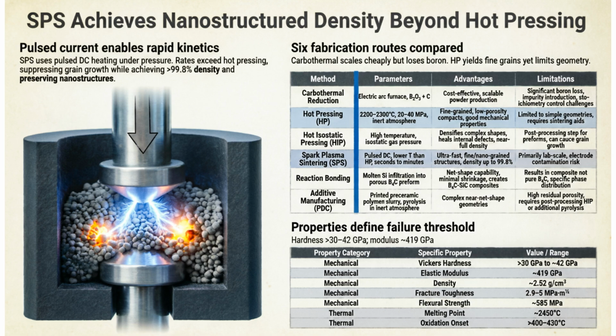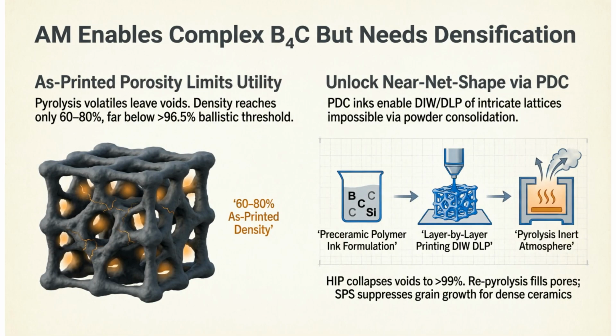Spark plasma sintering, or SPS, enables rapid kinetics and high density, helping to preserve nanostructures that might be lost during traditional hot pressing. Additive manufacturing allows for complex geometries, but currently faces limitations with as-printed porosity. Post-processing is required to reach the density thresholds needed for ballistic utility.